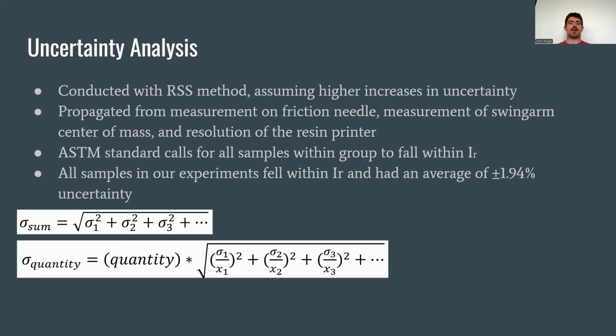The values that had uncertainty propagate from them were the angle recorded by the friction needle, the measurement of the swing arm center of mass, and the resolution of the resin printer. The standard deviation for each cure time for each resin was calculated to find the I sub r for each sample set. I sub r is the maximum allowable deviation between any two values in the data set, as listed in the ASTM value, equal to 2.83 times the standard deviation of that sample set. All of the data fell within their respective I sub r values, and the final IZOD values had an average uncertainty of plus or minus 1.94%.